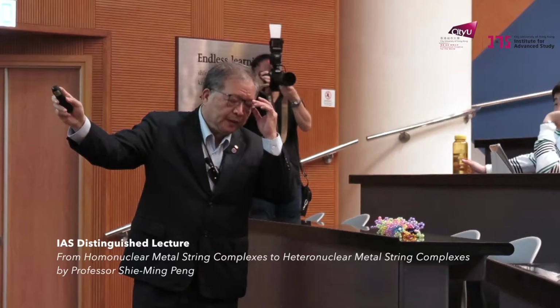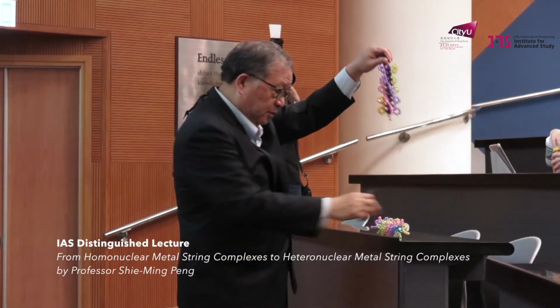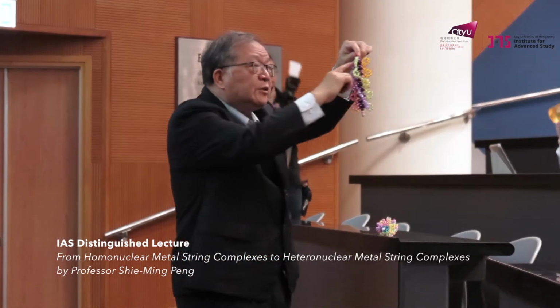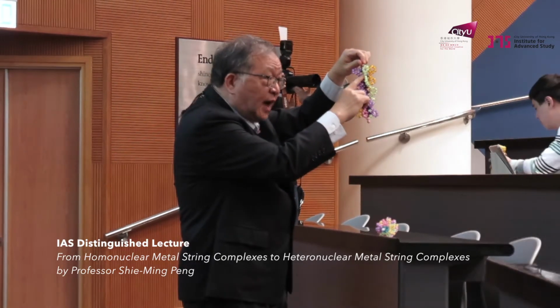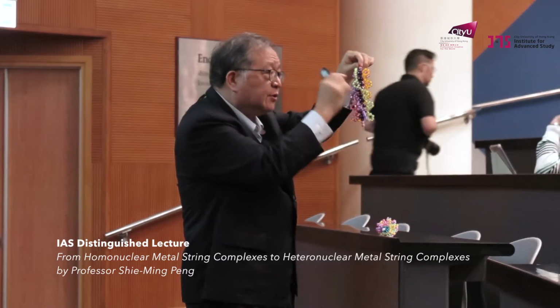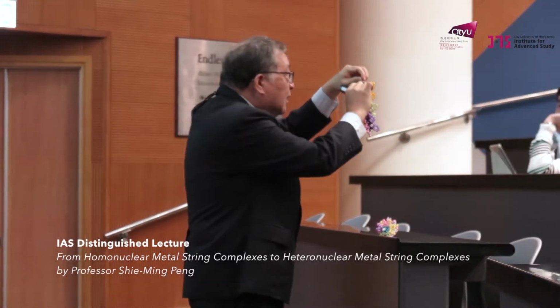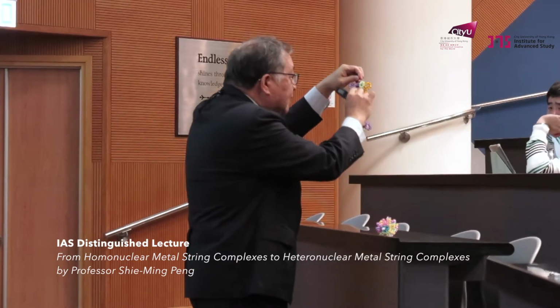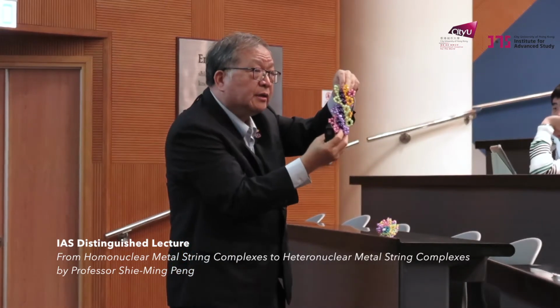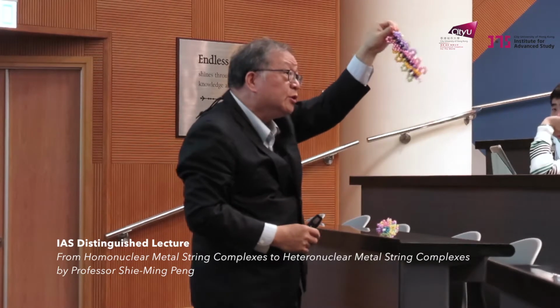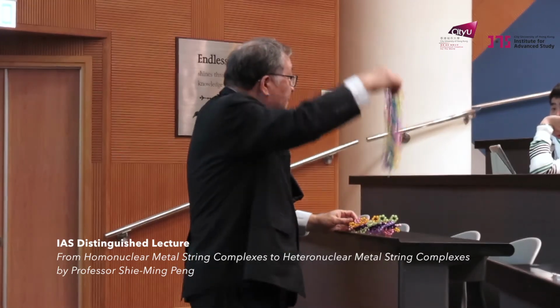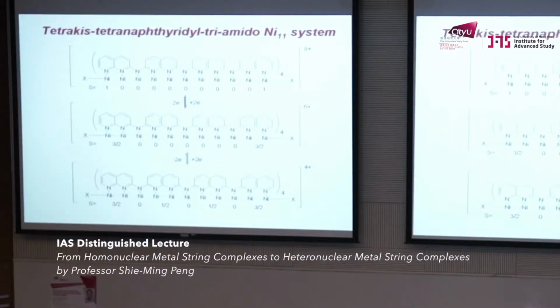Because that is anionic, those things are neutral. Those purely amido ones are neutral, because for every 2 nitrogen you have 1 negative charge. Quadruple, you have 4 negative charge. So 2 plus of this metal string will cancel out the charge. So if you keep lengthening the metal string, the metal complex is still neutral. This is a neutral one. This is a neutral one. But for the naphthyridyl series, it's different. You accumulate charge. For this example, you will have 4 plus. So it's very easy to reduce by 4 electrons at each naphthyridyl unit.